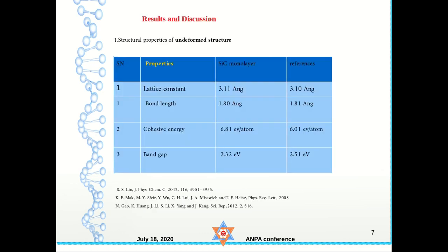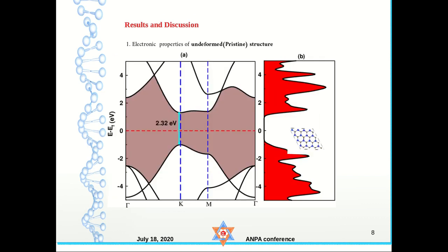These are the structural properties obtained after the calculation. The band gap is not very close but all other parameters are close to the reference values. These are the electronic properties of the undeformed, optimized equilibrium structure. We see a 2.32 eV direct band gap around the symmetry point K, and the DOS is shown alongside the band diagram.